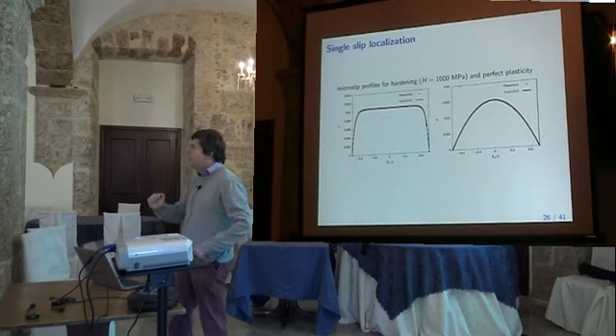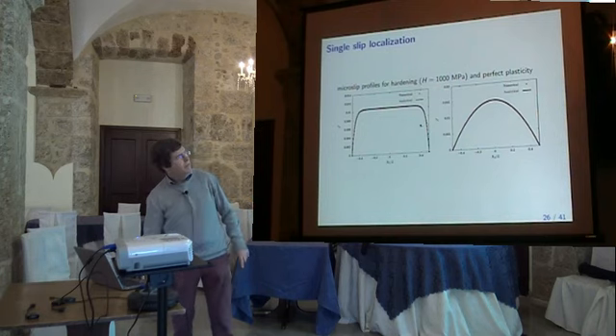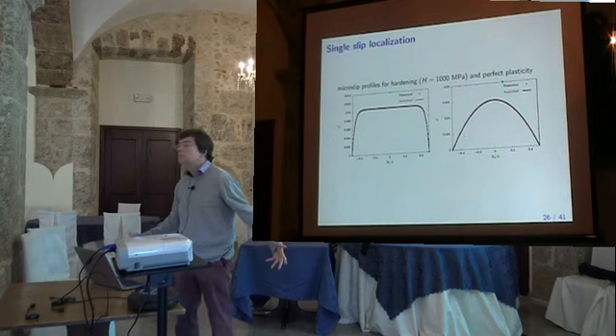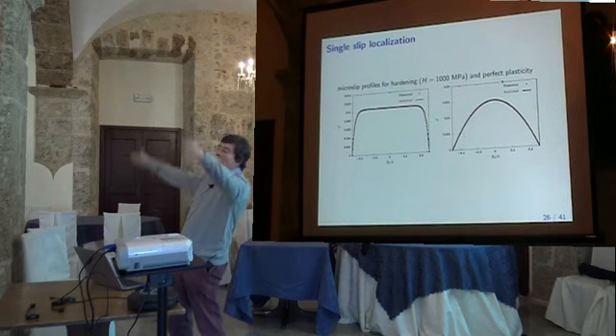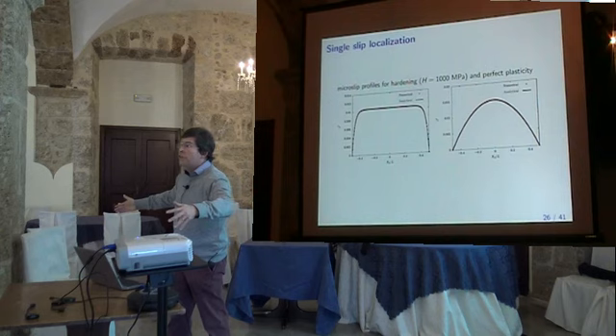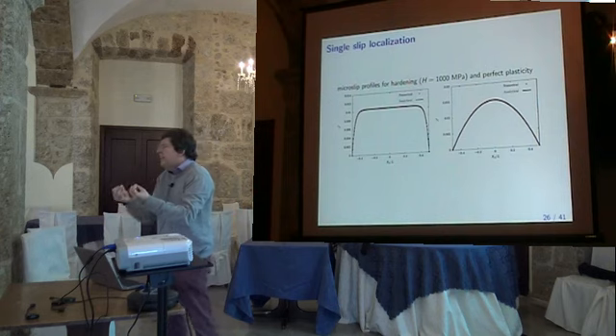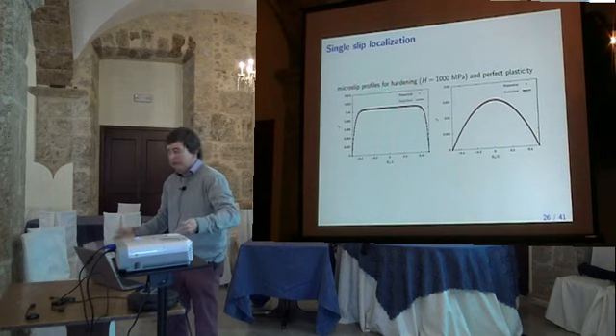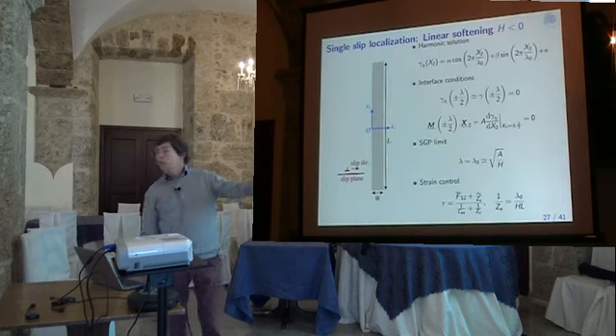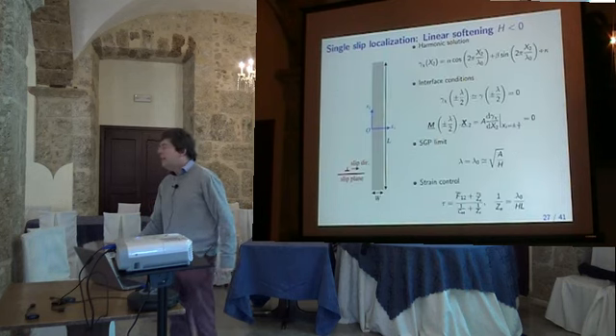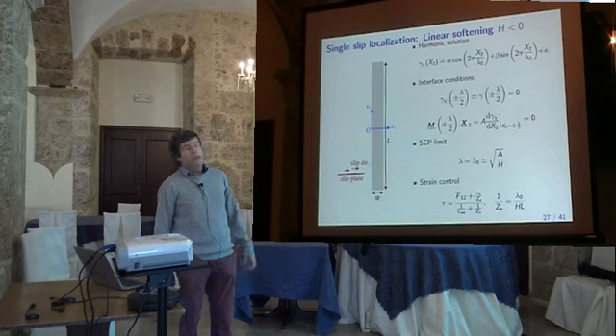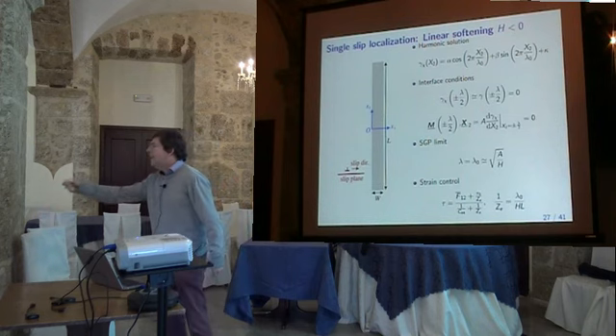Now, the parabolic case with the same boundary condition, you get a parabola. And if you have a larger zone, you will have a change of curvature. So there is no real intrinsic length scale, it is related to the size of the structure. Okay, and then we come to the negative case. So in the negative case, negative modulus, we get a harmonic solution with cosine and sine.